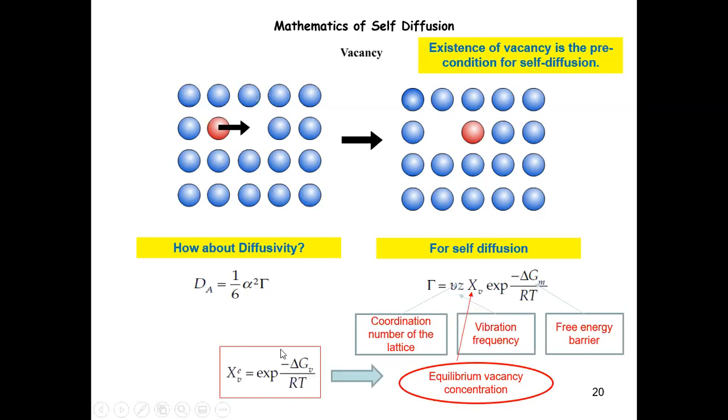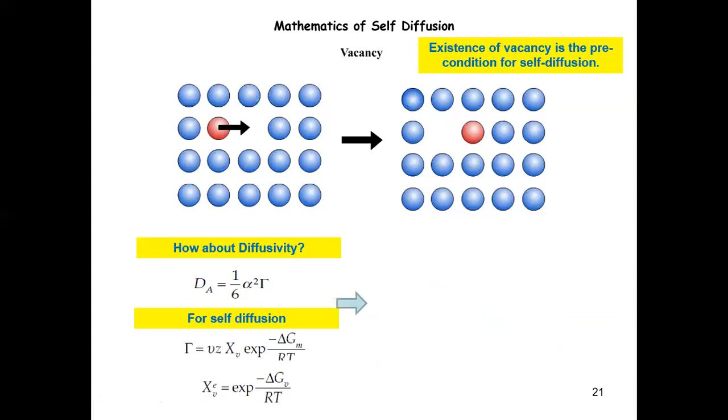So now what if we combine this vacancy concentration with the hopping rate that we worked out? You basically combine these two exponential terms together, right? And you see that's why you're going to have a much lower value for substitutional diffusivity compared to interstitial.